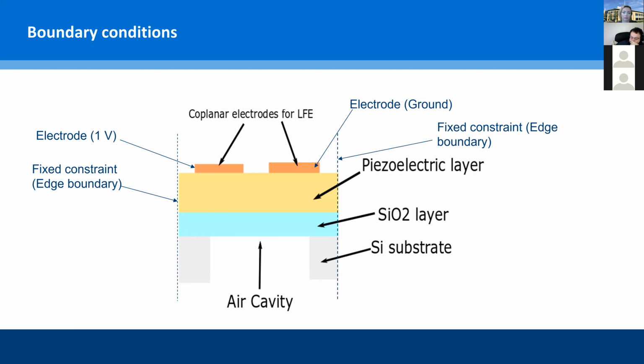These were the boundary conditions that we used for these acoustic resonators. As we discussed, amongst the coplanar electrodes, the left one was given an AC voltage of 1 volt, and the right one was grounded. At the edges, we used a perfectly matched layer, which was then followed by a fixed constraint. So the edges were mechanically fixed, and the air cavity was given the free constraint using COMSOL Multiphysics so as to enable the vibration of the device.